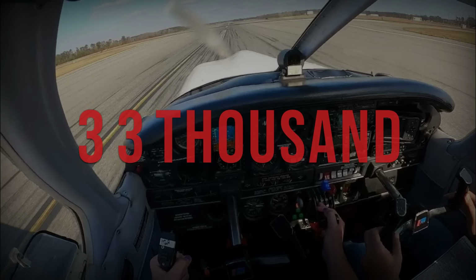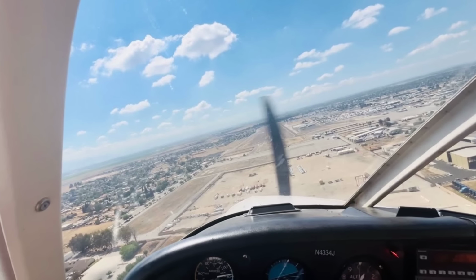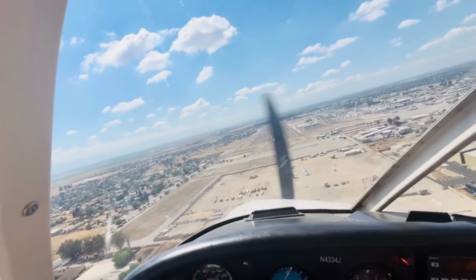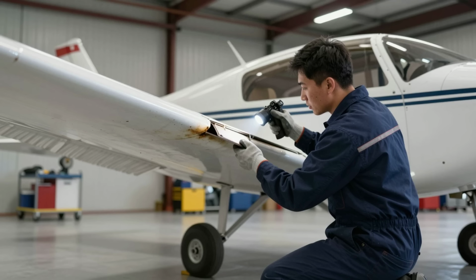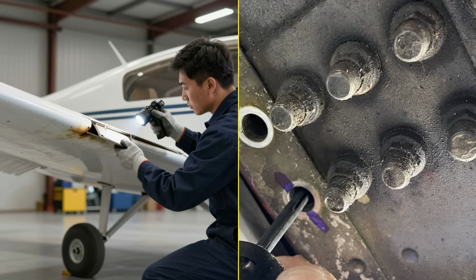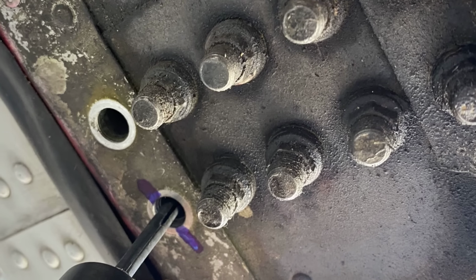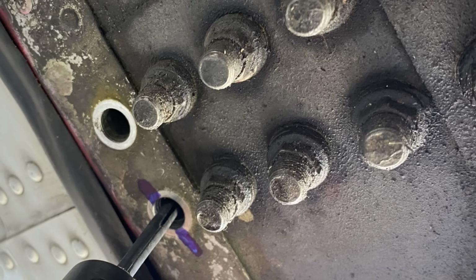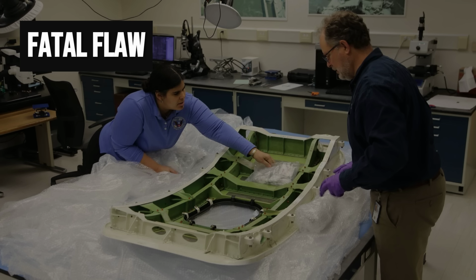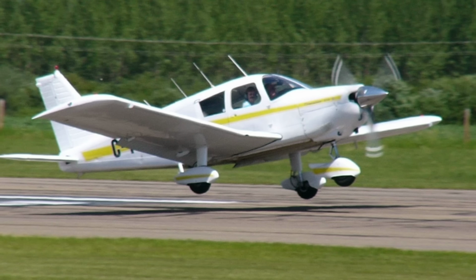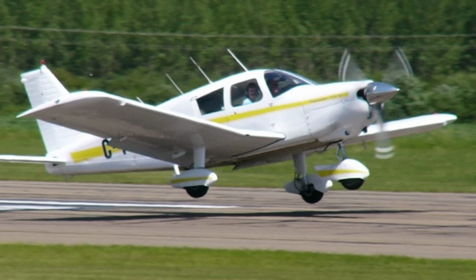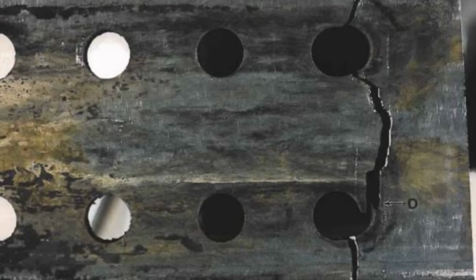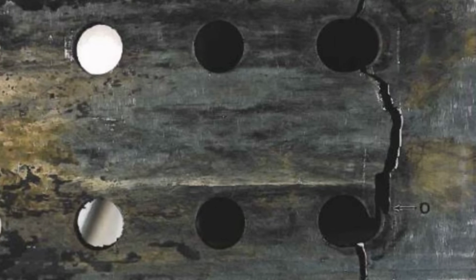The Arrow had survived more than 33,000 cycles of takeoff and landing, many of them in the demanding pattern work of a training environment. The inspection that could have found the crack was not required, and the area in question is not accessible during routine annual inspections. The NTSB Structures Laboratory called out the fatal flaw, a fatigue mechanism driven by high cycle use, concentrated at a bolt hole in the lower spar cap, and invisible to standard visual checks.